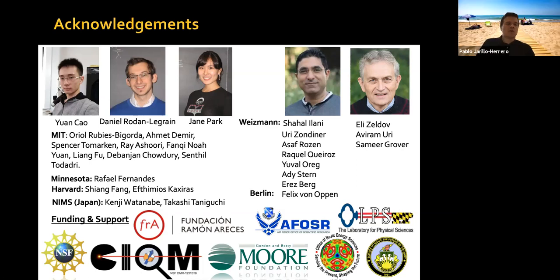Very good. So unfortunately, we do not have local information on the twist angle for each of the devices that we measure, okay? Because we cannot do scanning local measurements. You can measure the twist angle via different techniques, STM, scanning SET, scanning nanosquid, as Eli has shown. We fabricate some devices, we send them to Weizmann. Sometimes we go ourselves also to help at Weizmann.